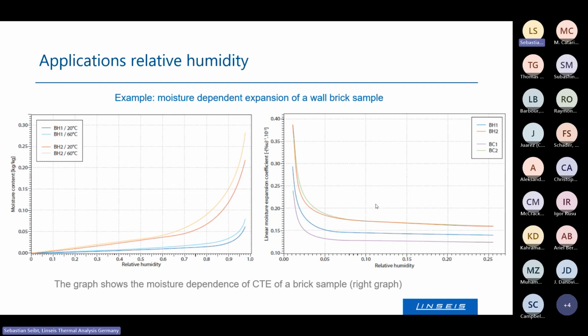On the other experiment, on the right side, the humidity level was increased and the coefficient of thermal expansion was measured multiple times. By increasing relative humidity, the coefficient of thermal expansion suddenly decreased from quite significant values to significantly lower values.